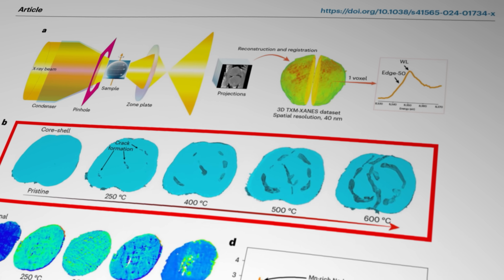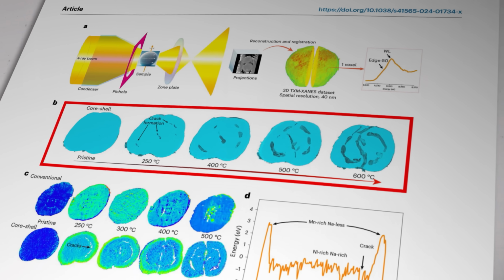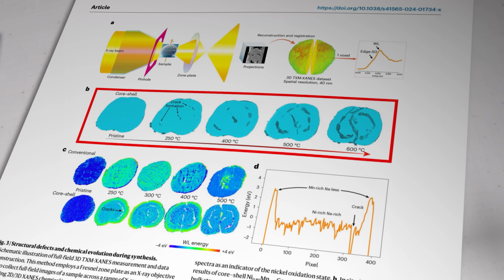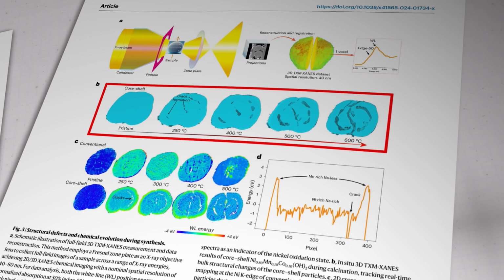The strong inference was that the distinct boundaries between different metals in the traditional gradient configuration were setting up their own so-called microstrains. In other words, it looked very much like the problem was in large part being created by the manufacturing process itself, rather than the charge and discharge cycles that occurred during the cell's operation. And that was a fairly important piece of insight.